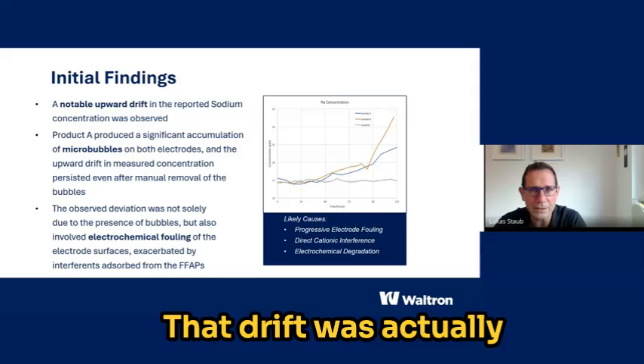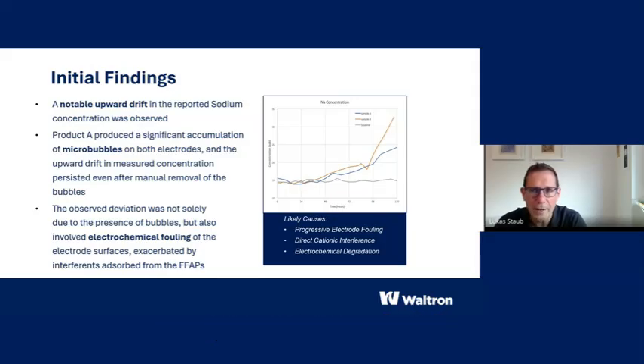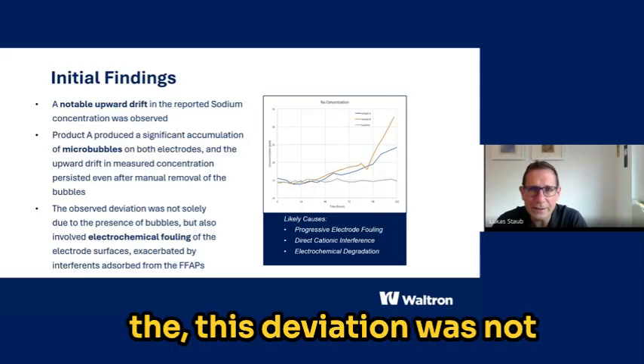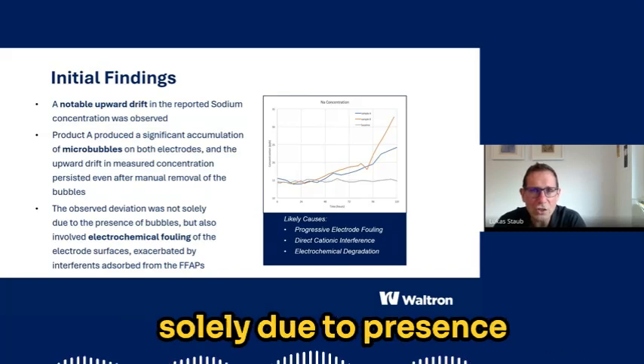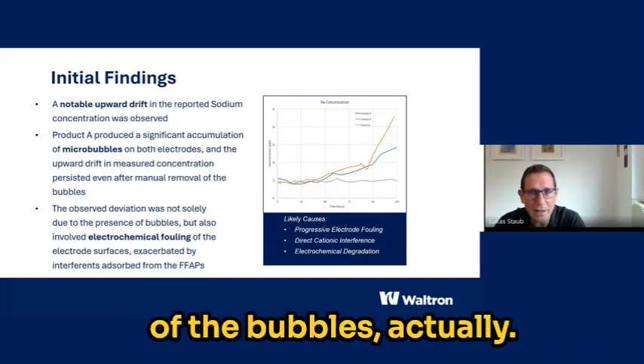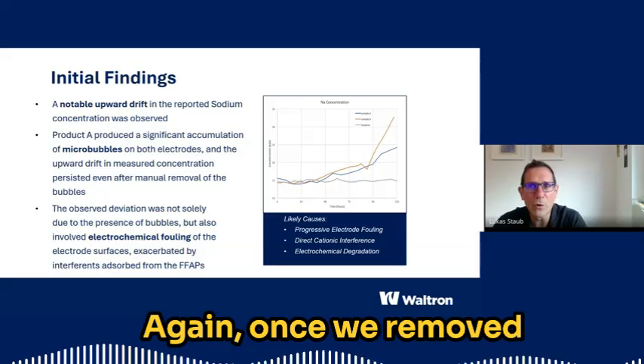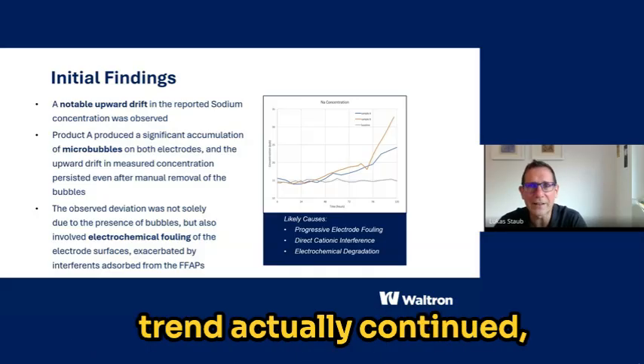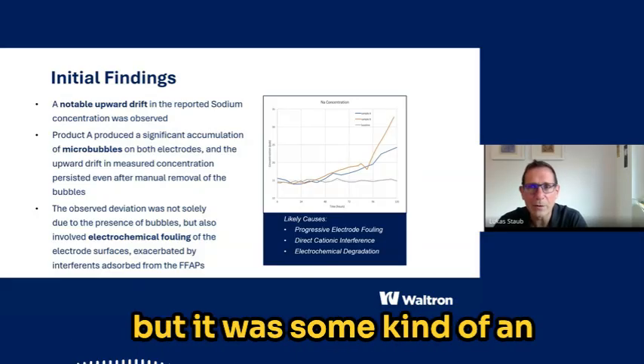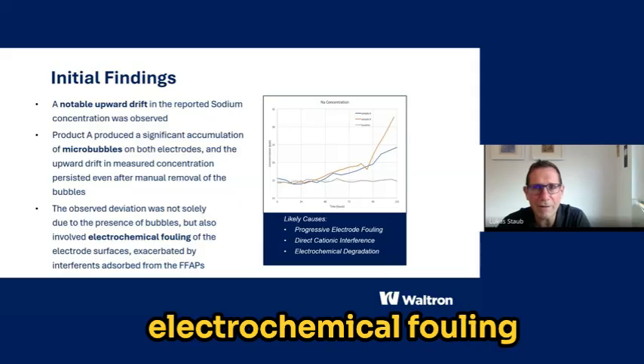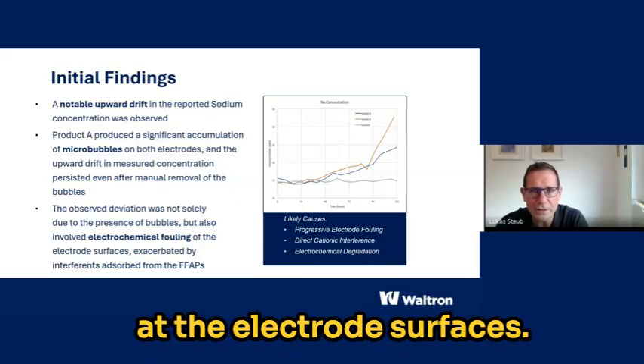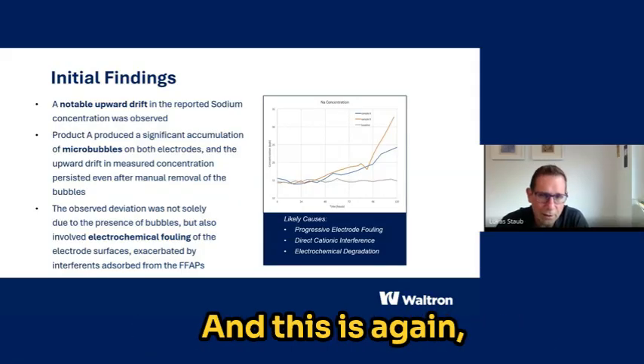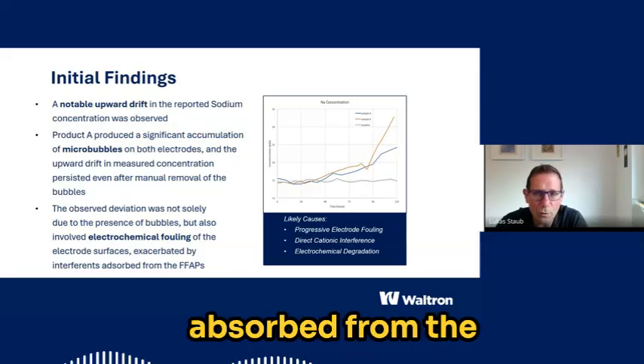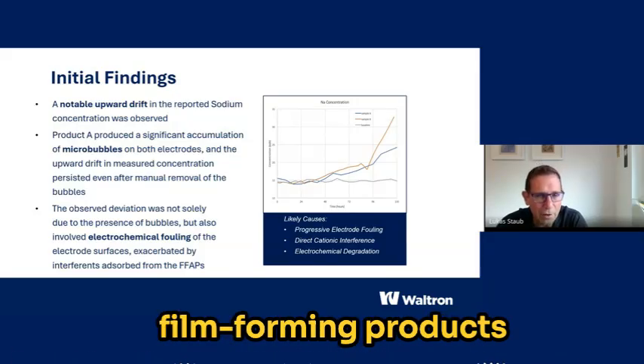That drift was actually very persistent. And it was observed that this deviation was not solely due to the presence of the bubbles. Again, once we removed the bubbles, this upward trend continued, but it was some kind of electrochemical fouling of the electrode surfaces. And this is, again, interference absorbed from film-forming products.